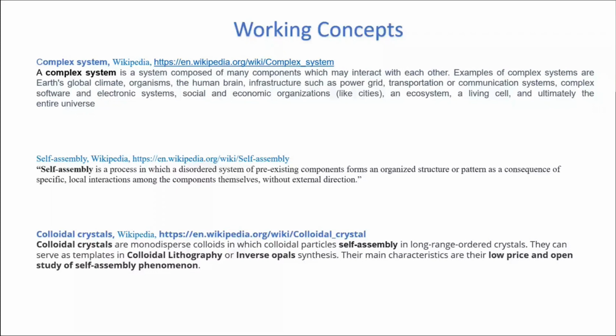We study this phenomenon usually by using a colloidal solution of spherical, submicron spheres, which, by putting a drop or a film on a substrate, after the solvent evaporation, we obtain a solid of close-packed spheres, which in some conditions are ordered in a final pattern. These patterns are usually called artificial opals or colloidal crystals.